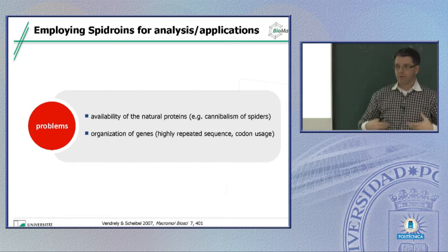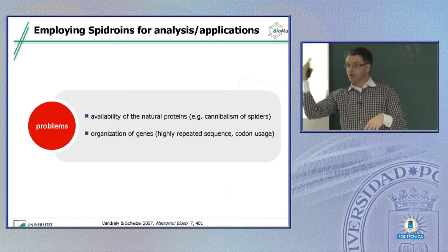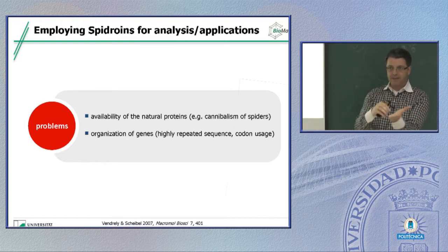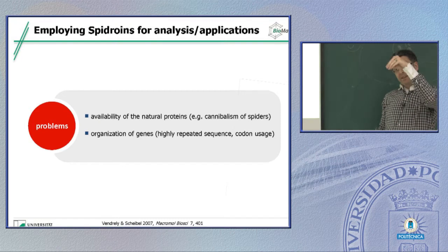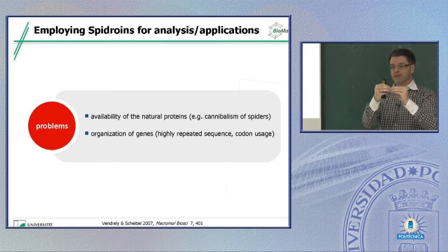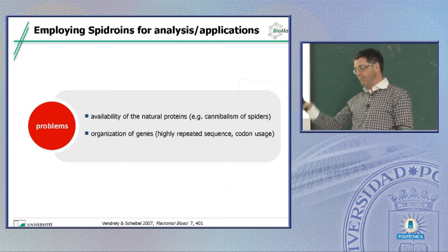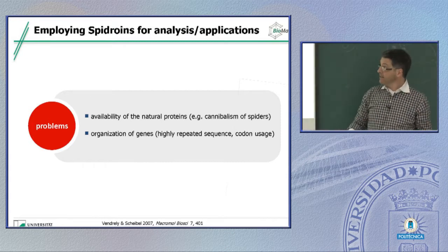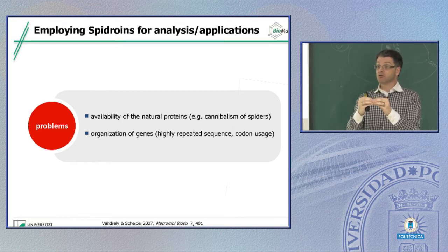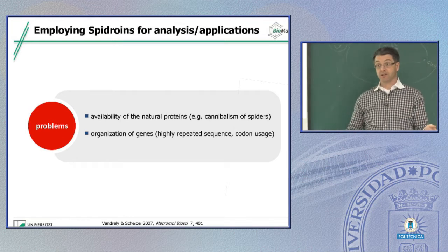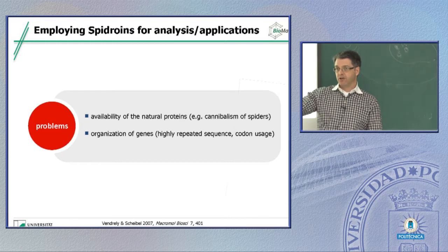I mean, if you use silk for textiles, there are even technical qualities that differ good performing from low performing silk. You even can see that if you have a cocoon of silk just by color, for instance. But even with an individual, the quality of a silk differs depending on the day, on the environmental conditions, temperature, humidity, on the diet. And this makes it very hard to get reproducible characteristics to a product, especially if we talk about biomaterials. We need high precision products that perform every day in every patient identical.